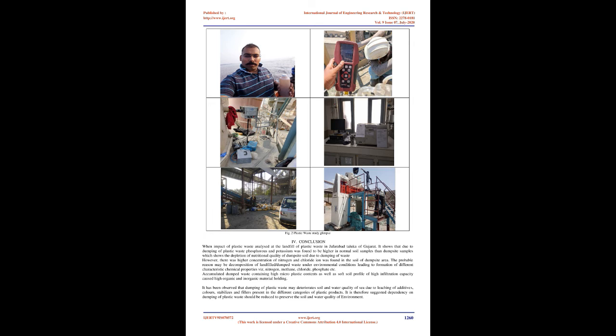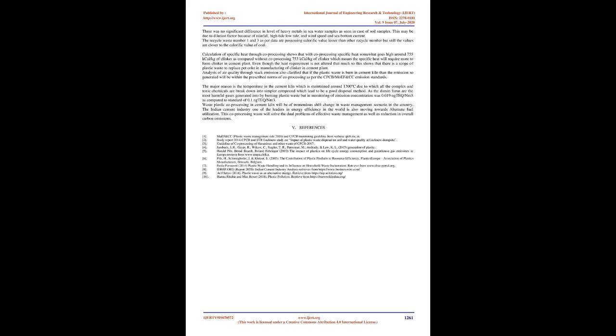Stack monitoring to study the impact on air quality. The emission analysis was performed as per the methods and standard operating procedure of emission testing in hazardous waste incinerators published by the Central Pollution Control Board, September 2007 edition. The major reason is the temperature in the cement kiln, which is maintained around 1300 degrees C, due to which all the complex and toxic chemicals break down into simpler compounds, making it a good disposal method. Dioxin and furan are the most harmful gases generated by burning plastic waste, but